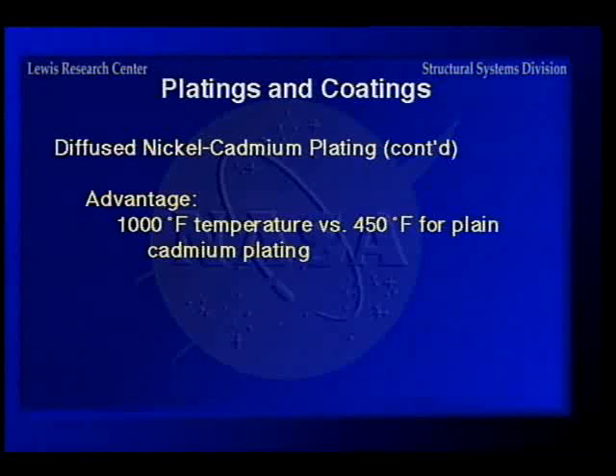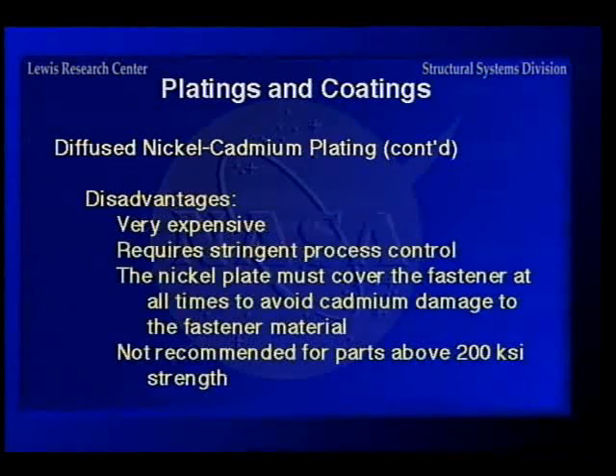But once again, it's expensive. You have to have extremely close process controls, and the nickel plate has to cover the fastener at all times to avoid cadmium damage to the fastener material. And it's not recommended for parts above 200 KSI strength.